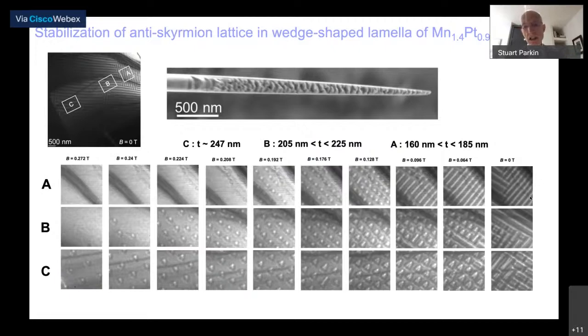So what is interesting is that the stability of the anti-skyrmions is much greater than that of Bloch skyrmions observed in the B20 compounds, which have been extensively studied. The anti-skyrmions appear over a very wide range of magnetic field and temperature, almost up to the Curie temperature, and they can be stabilized even in zero magnetic field.